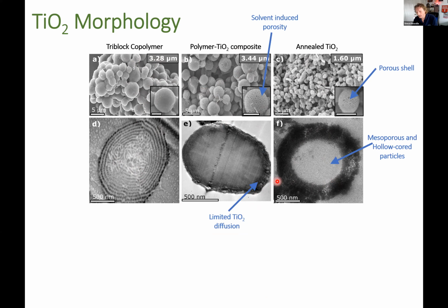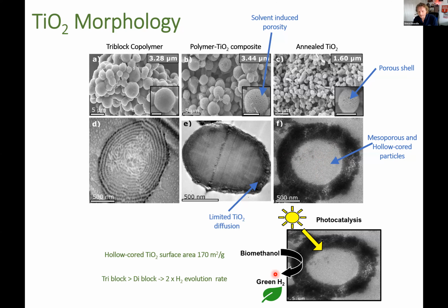It turns out that the titanium isopropoxide doesn't penetrate all the way to the middle. It just penetrates into the outer layer here. So when we do the annealing, we end up with an outer layer of a very porous titanium material, and inside the particle is completely hollow. There's nothing present. So we've looked very carefully at the surface area of these materials, and it turns out to be reasonably good.